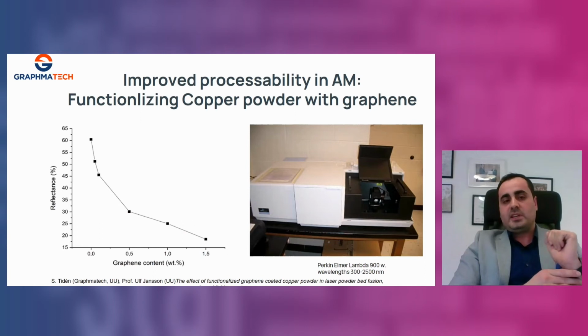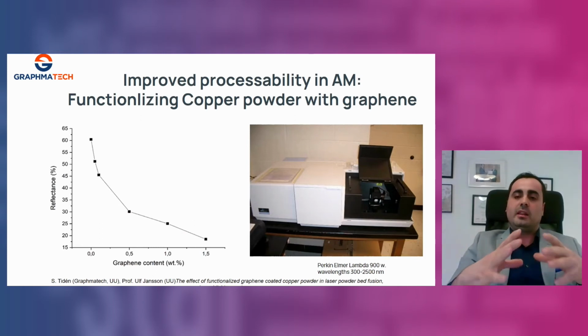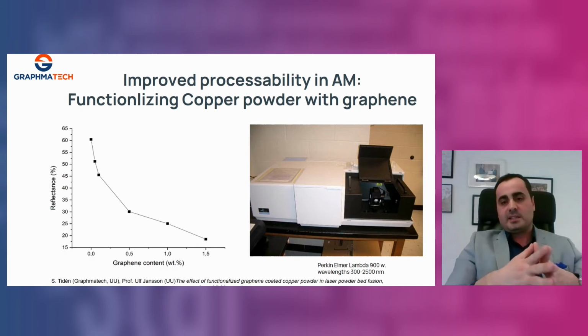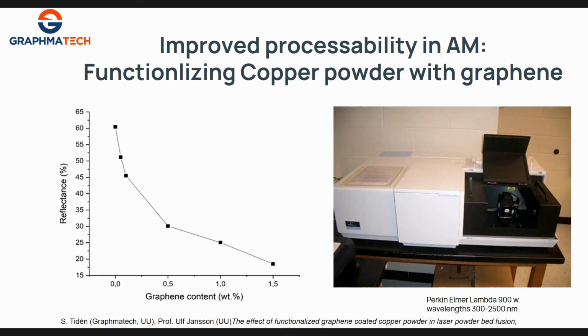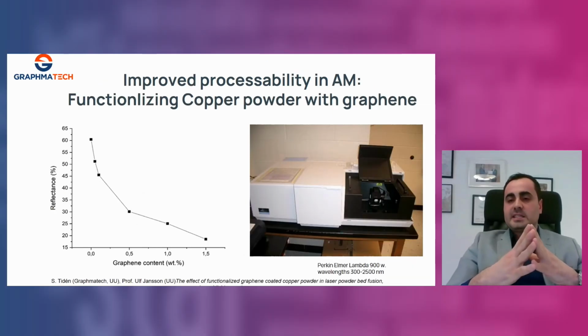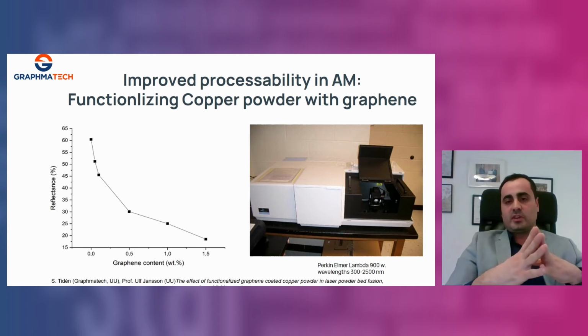So here to the left, you see the relationship between the graphene concentration in the coated powder and the reflectance as it has been measured in this device. And this is still under publishing work together with our collaborator at Uppsala University. There you can see that the graphene has dramatically improved the absorption of laser of copper powder. The improvement was at the level of 67% at the highest concentration of graphene. However, the highest concentration of graphene is not always the optimum. Here you have to find the balance between the improved absorption of laser and the properties or the added value from the graphene coating.